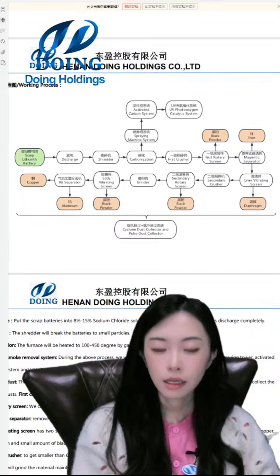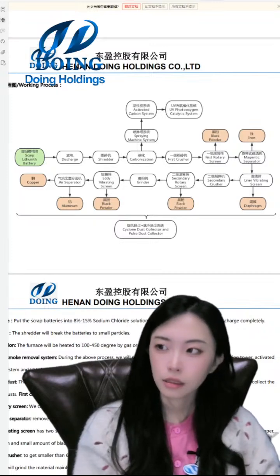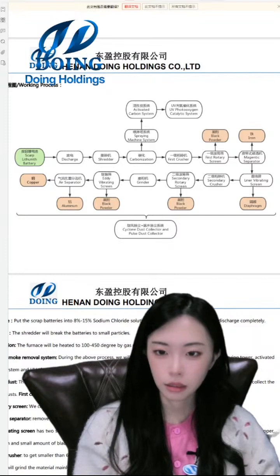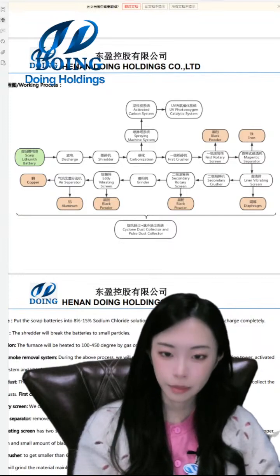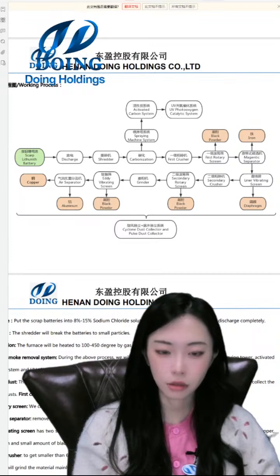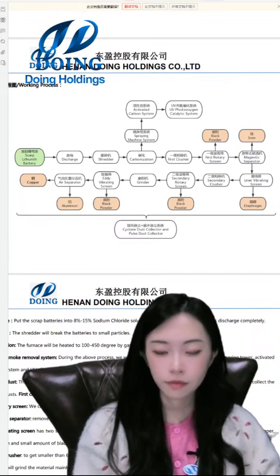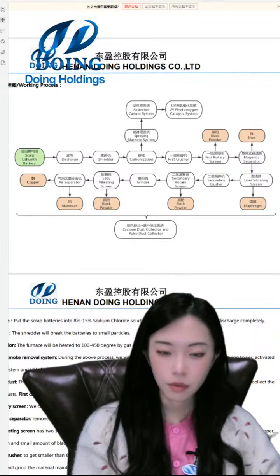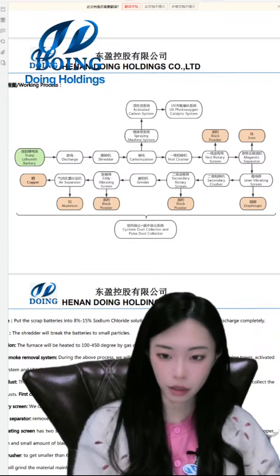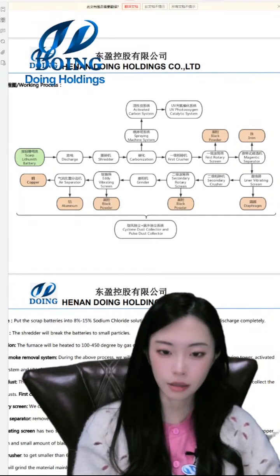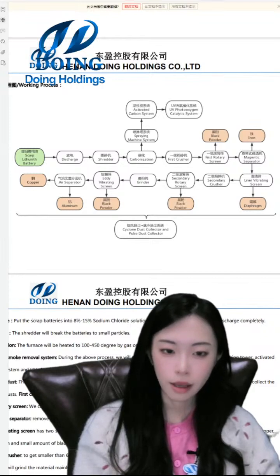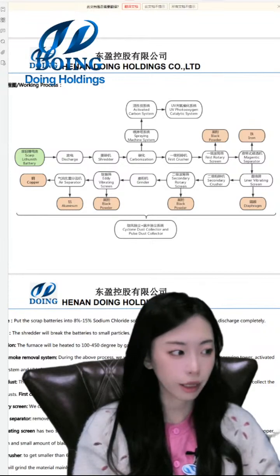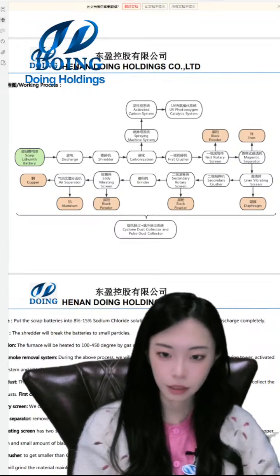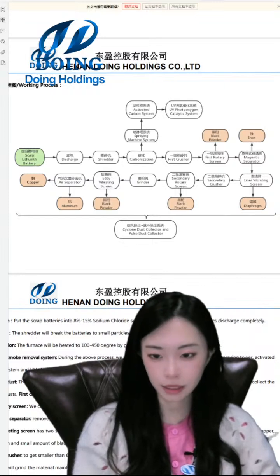And then the air gravity sorter will be used to separate the copper and aluminium. It combines the action of the airflow and the vibration friction on the materials, while the large particles, the copper, will settle to the bottom, and the smaller aluminium particles will suspend on the surface of the layer. By the action of the airflow, we separate them, and they go out through different outlets. In this link, the recovery rate of the copper and aluminium is about 98%.